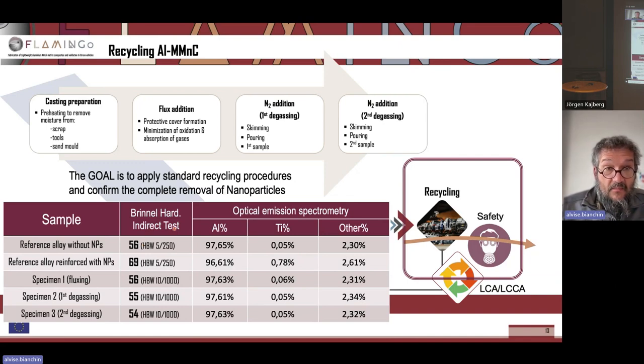And this is most effective when we have elements in the nanoparticles that are matching with elements in the aluminum alloy matrix. In the case where the elements are not matching, then we can use the optical emission spectroscopy to assess the amount of, for example, titanium, which is directly related to the titanium carbide in the material.